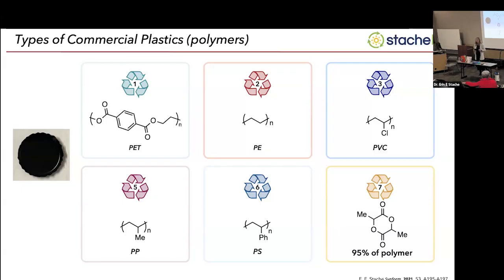But PLA has a lot of great properties. It comes from a biorenewable source. It comes from lactide. And it's pretty benign in terms of the plastic itself and the lactide monomer. They're pretty safe for you. The problem is lactide is pretty expensive to make. And so chemical recycling, converting the plastic back into the monomer, is really the best way to recycle it and would be the way to increase our dependence on PLA. And it turns out we can do this almost quantitatively using our technology.